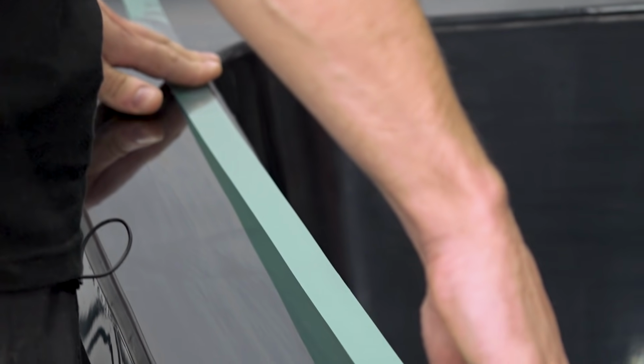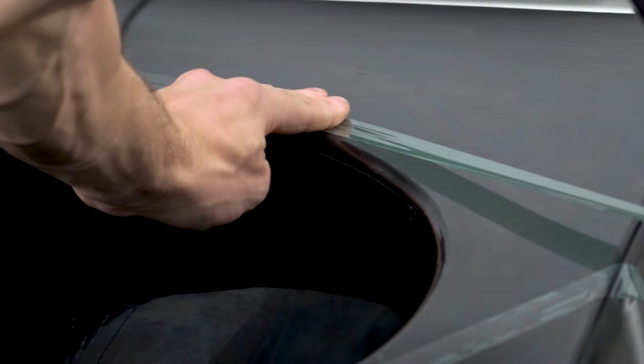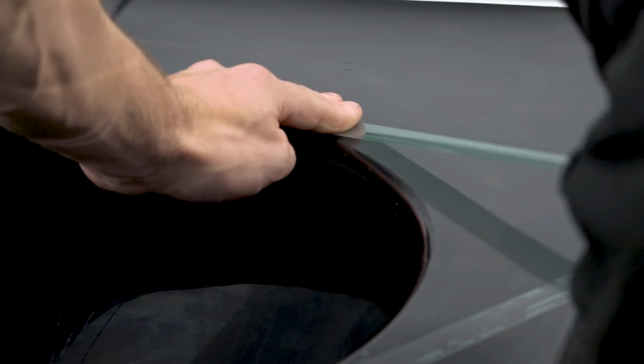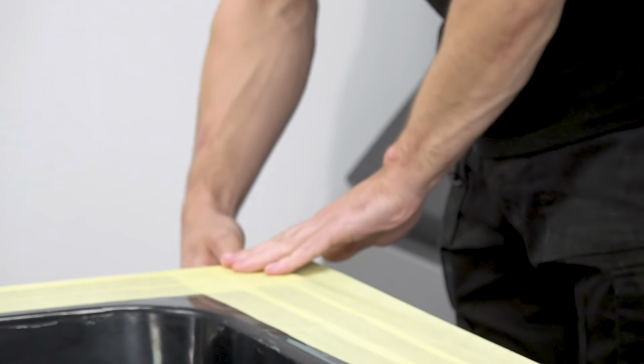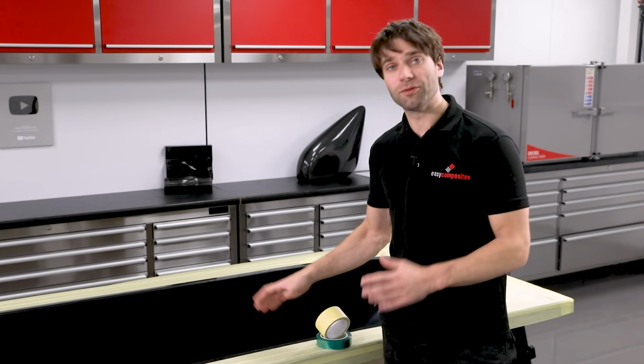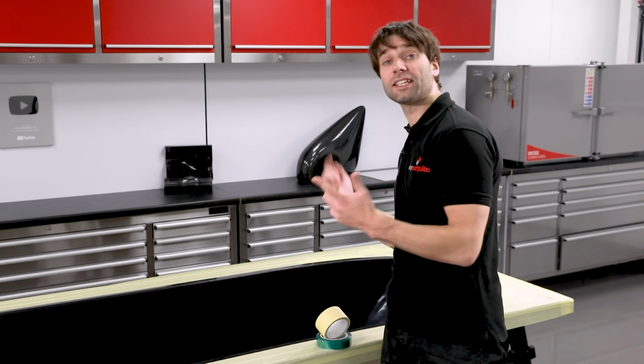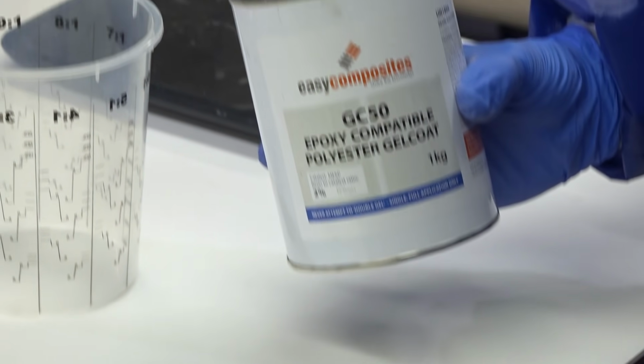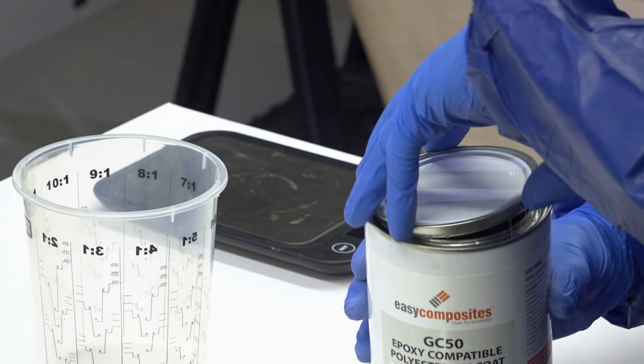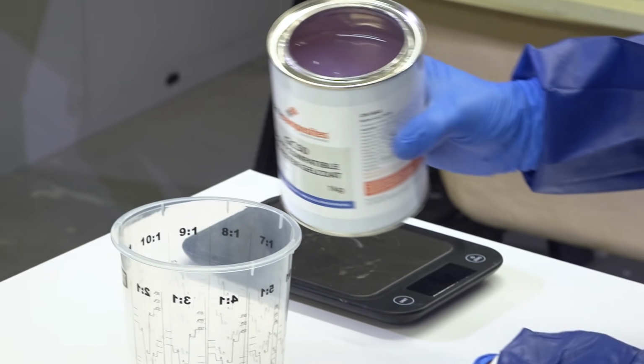If you're going to be spraying a gel coat, the mould flange will need to be masked using a flash release tape to keep it clean from any overspray. With the mould now fully prepared, we're ready to put down the gel coat, so we'll just take this now through to the booth. The gel coat we're using is our GC50 epoxy compatible polyester gel coat.